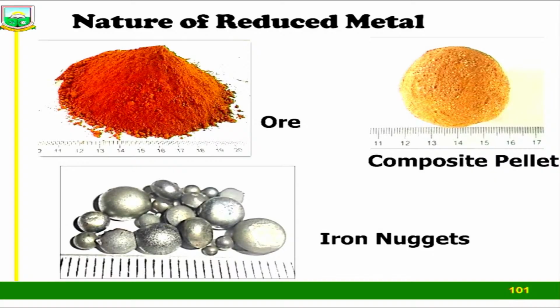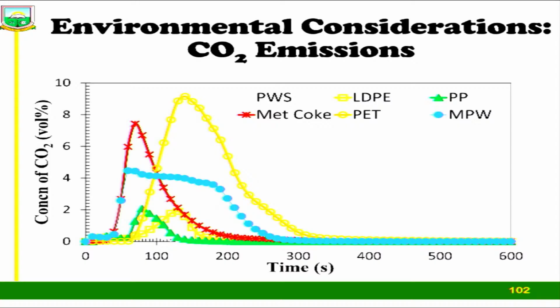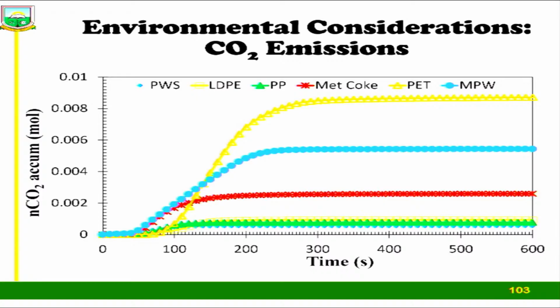When we tested for this metal using the inductively coupled plasma optical emission spectroscopy, ICP-OES, we were able to get an iron content that ranged from about 95 to about 99%. The rest was only carbon. Again, the superiority of the polymers over waste plastics, over the conventional material is also shown over there.